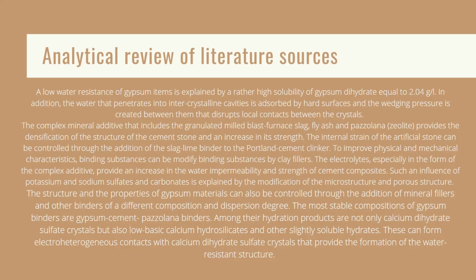structure. Based on the conception of the contribution made to low water resistance by the wedging effect of the water concentrated in the contacts between the individual crystals and particles in the structure, it was suggested to use a relative linear humidity strain caused by the water saturation, swelling, epsilon, as an additional indicator of water resistance.